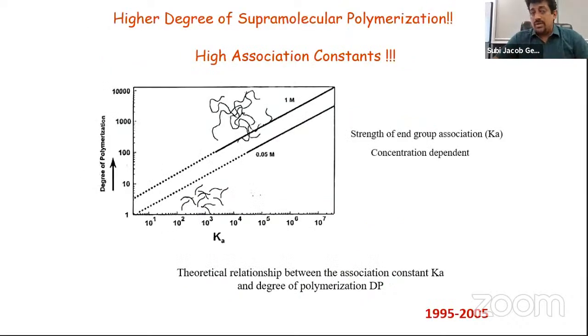One of the major problems was these theoretical studies. You know that polymeric properties are determined by molecular weight. If you want an appreciable molecular weight, which is very important for mechanical properties, you should have a reasonably high molecular weight. This theoretical study says that if you want a degree of polymerization of 1000, that's the number of monomers in a polymeric chain, with the x-axis being the association constant, you need a very high association constant. So 10 to the power 7 between the monomers if you want a high molecular weight polymer.